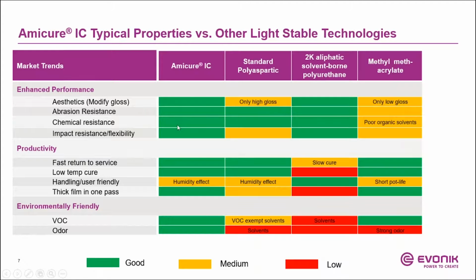Abrasion resistance, I have most of them in green. Again, these are top coat technologies that work really well with abrasion resistance and chemical resistance. Pretty much they're all in green. I do have MMA in orange because, again, slightly lower abrasion resistance and chemical resistance. They are poor, again, with organic solvents. Impact resistance, again, these compare more towards the urethanes. Again, it has high strength, but also high flexibility. Standard polyaspartic and MMA tend to be hard, but then also slightly brittle.